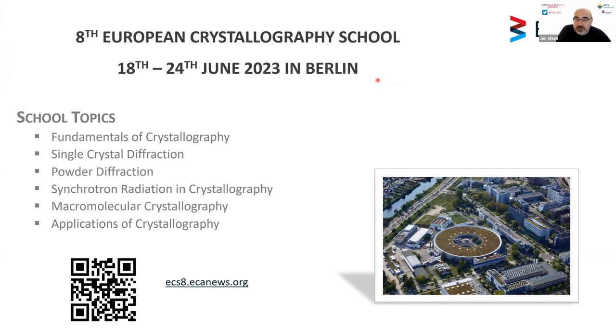Yeah, so it's maybe not the technique that is really needed for co-crystallization, but for instance, we did some experiments where we were interested in nanoparticle formation under mechanochemical conditions. And therefore, it would be a really good add-on to see the particle sizes early in the formation. That is something that you cannot capture with X-ray diffraction. You see then really existing crystals, but not the smaller sizes for comparison. In the field of co-crystallization, it might only be helpful if we look at super small particles formed at the beginning.